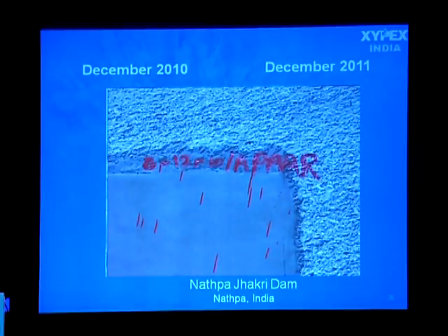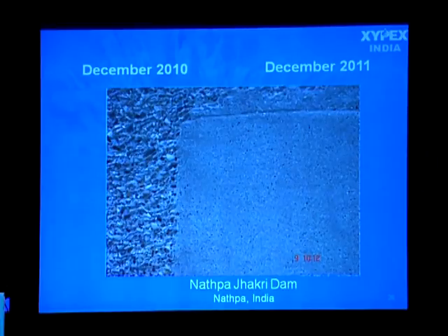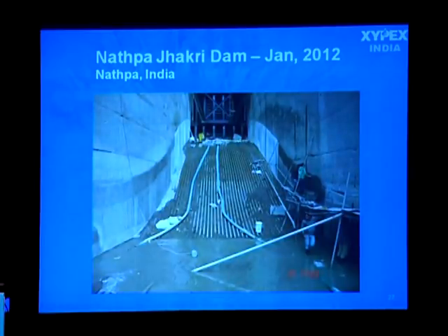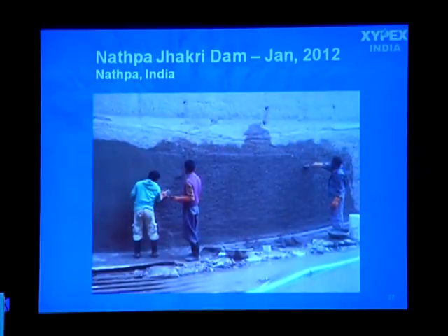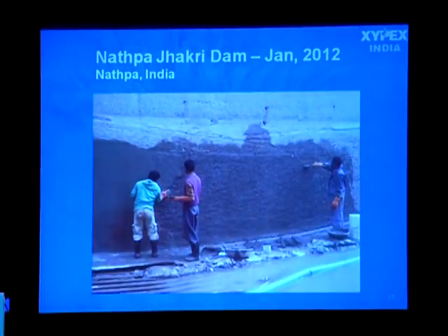And then after a season of 12 months, we went back and did the observation. There was a very, very minimal loss of this high strength repair material. Subsequent to that field trial, we were actually authorized to repair the entire spillway piers using this high strength repair material, and then we did it in 2012, and then subsequent gates were also done in the same year. As of now, as I speak, we have almost crossed 4 years now, and that treatment is still holding intact. So there is no problem as far as loss of any surface erosion is concerned.